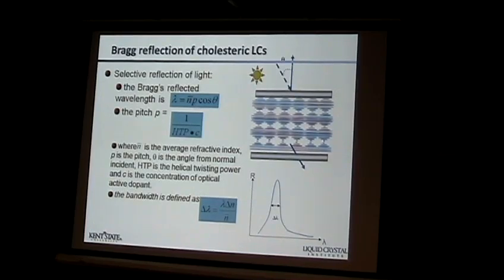Okay, so this is kind of basic, between these cholesteric materials under this electric field. In general, you can also change the structure property. For example, if you are interested in reflecting all the visible light, broadband, then you change the Δn. Δn is roughly around 0.6 for this material. If you have a high Δn, about 0.6, then you can cover the full visible spectrum, roughly from 400 to 700. And in that case, you can have black and white.